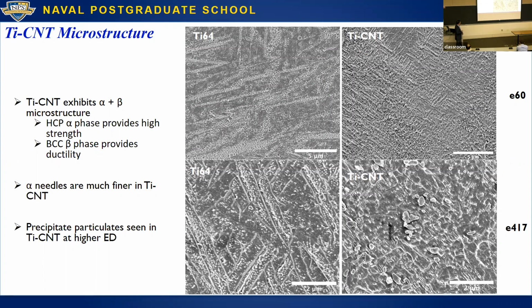This is SEM of the microstructure. Here you get a much better view of just how much finer the structure is with CNTs. The needle structures are much finer at equivalent energies. And then also as you go to higher energy, in both cases, it becomes finer. You'll also notice here these particulates that evolve in the Ti-CNT case. And this only occurs in the Ti-CNT.